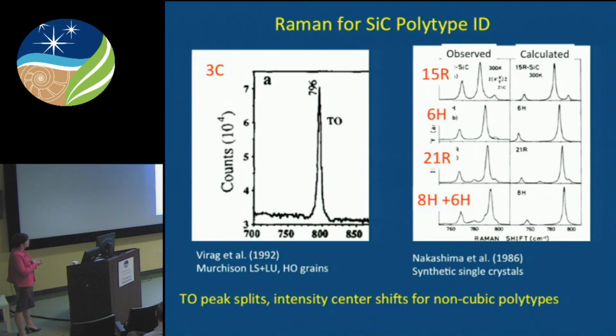Another way, that's not quite so painstaking as the TEM work, to identify the polytype of silicon carbide is through Raman spectroscopy. If you have a nice large single crystal of silicon carbide, you can use your Raman spectrometer to get a clear signature of which polytype. The 3C, the simplest polytype, has a transverse optical mode that's triply degenerate, so you get this one nice sharp peak. These other crystal structures, so this is 15R rhombohedral, and this is 6H hexagonal. The number just refers to how many of those bilayers are required to form that larger crystal structure.